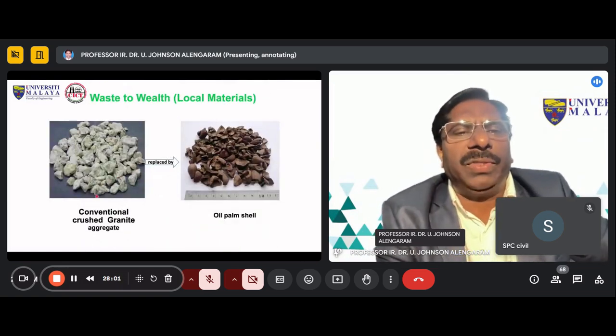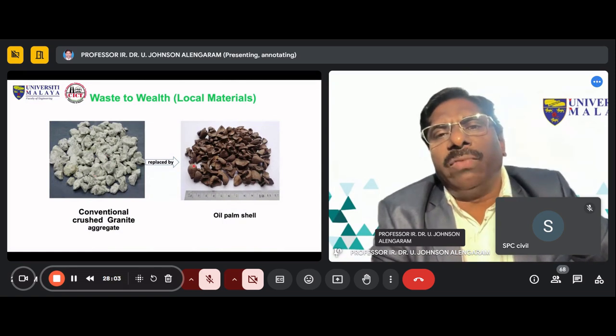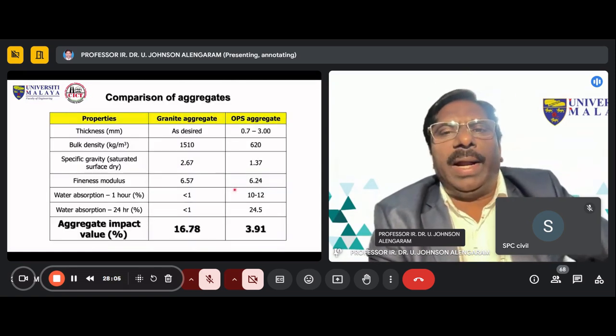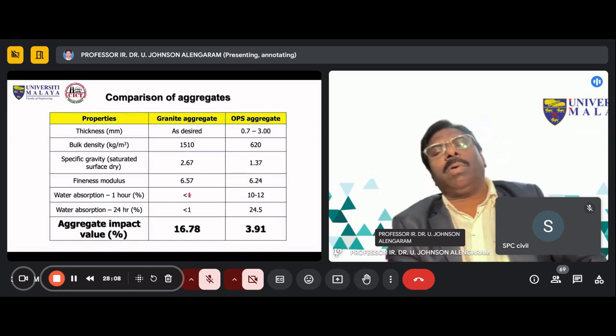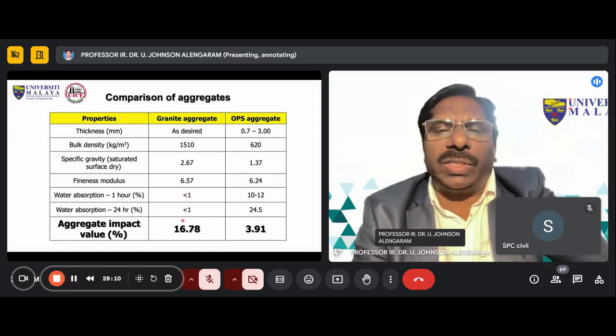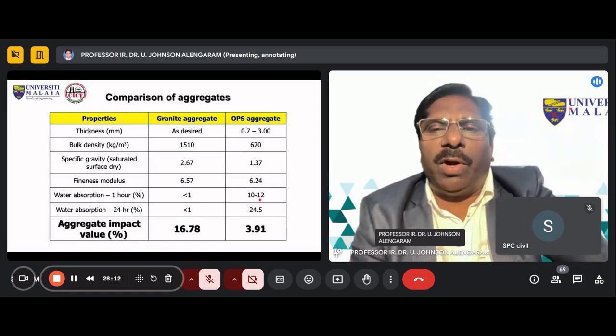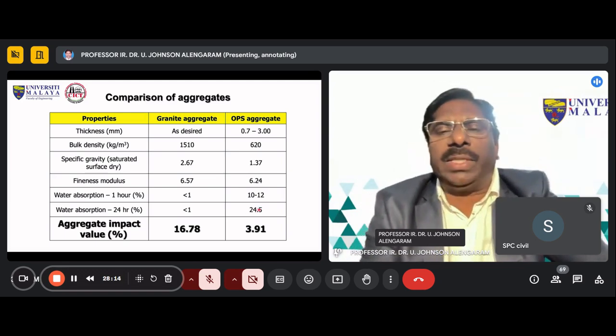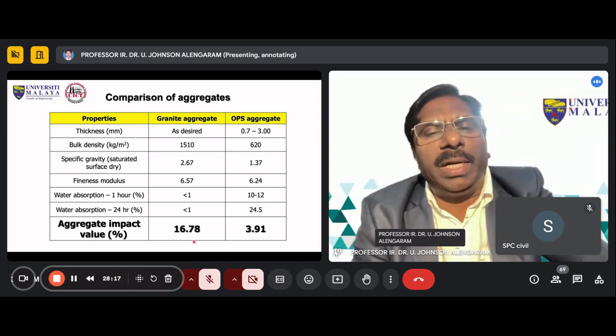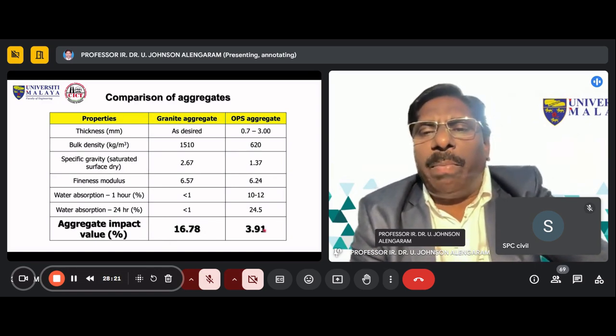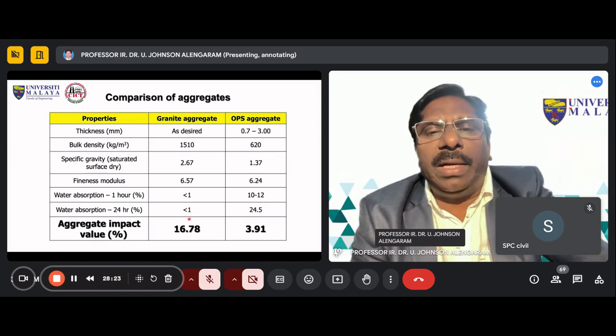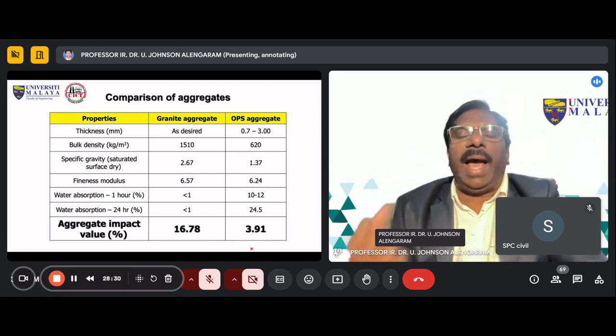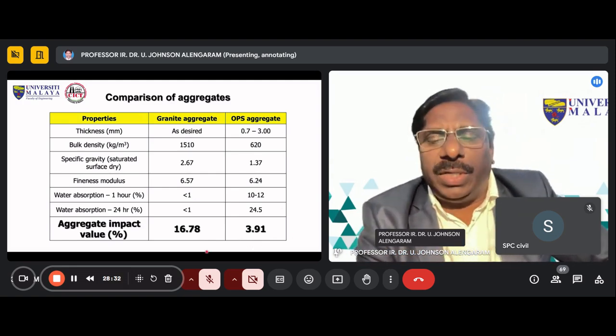And you can see we replaced the conventional crushed granite with the oil palm shell. The property with the most interesting feature is the aggregate impact value. Of course, the water absorption was quite high, but nevertheless, the important characteristic that we utilized was the aggregate impact value. When you compare the crushed granite and the oil palm shell or palm kernel shell, it is one quarter of this. Therefore, we can take more impact without crushing the aggregate.